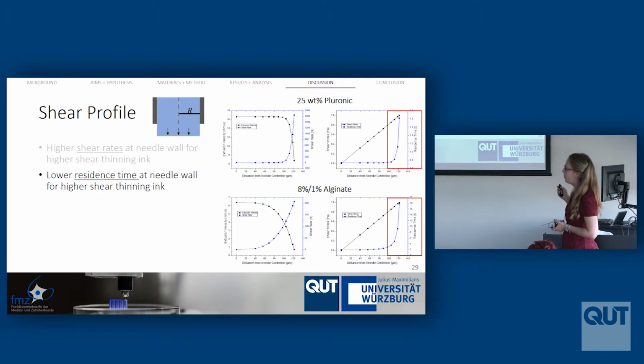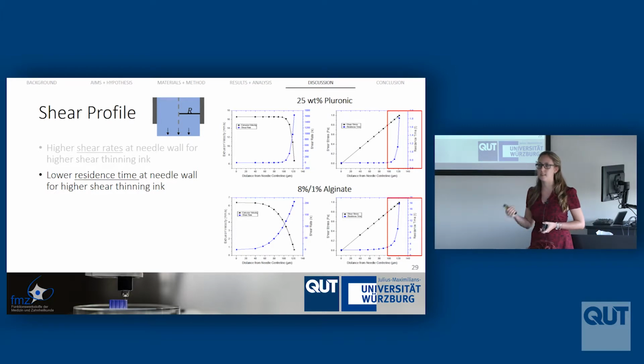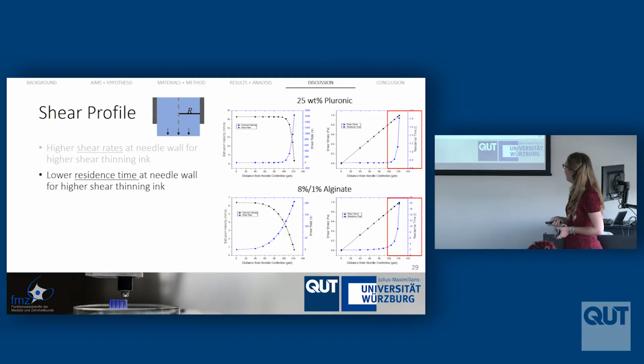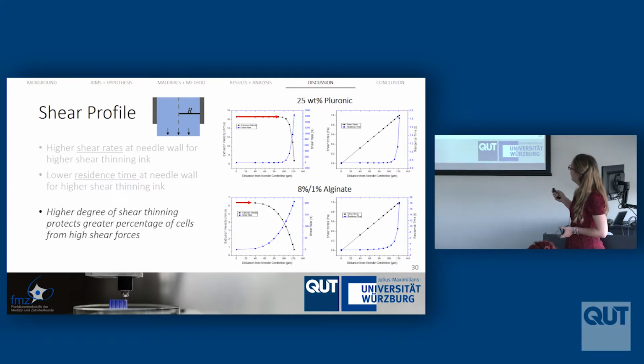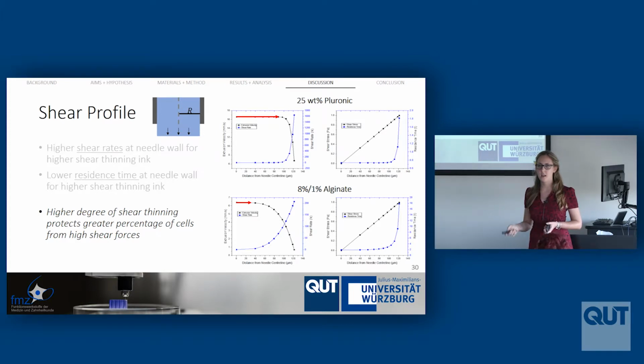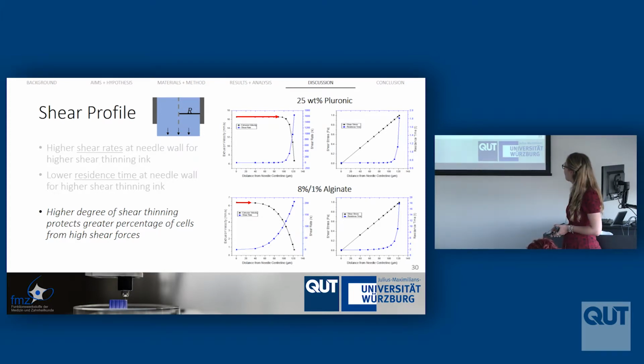These residence times are about 1.8 seconds. So that's all that's experiencing these high shear forces. But for other kinds of materials, these are up at around 18 seconds. So it means a cell is being exposed to these shear forces for a whole lot longer and ultimately could be reducing the viability of our constructs because we're killing the cells just as we're dispensing them through a needle. So we can see the difference here. More cells are being protected by these rheological properties as opposed to these very small ones. So only a small percentage of cells are being protected, whereas all of these ones are being exposed to these very high shear rates that could be affecting the biocompatibility as well.